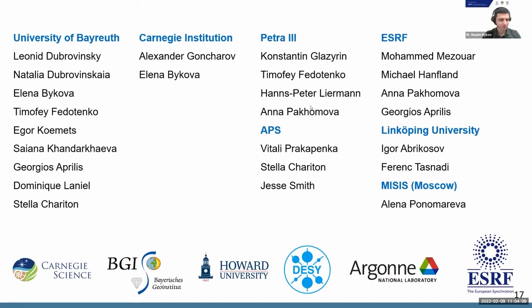Yeah, this is the direction which we are actually thinking about. Usually we have a big piece of osmium in the center of our diamond cell, and we have a phase distribution starting from osmium N2, for example, and more nitrogen-rich phases towards the boundary of the osmium piece. What you suggest is what we are also thinking about, to really start with a big excess of nitrogen over osmium everywhere, but we did not do this experiment. So we are basically dealing with a multi-phase sample too, but then we just pick up all the phases which are present in the sample afterwards. Okay.